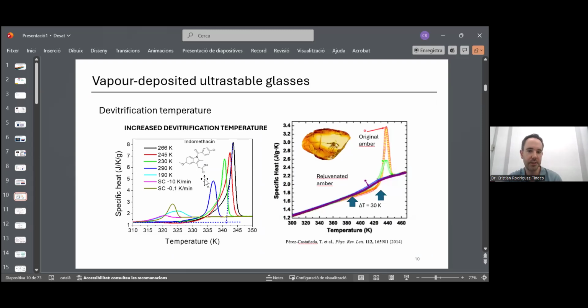Here we can see some examples. So it was with indomethacin, which was one of the first molecules with which the concept of ultrastable glasses was tested. And these are calorimetric measurements. We see here these small bands. These are the ordinary glasses, the glasses that have been formed by cooling from the liquid, at 10 Kelvin per minute or at 0.1 Kelvin per minute. The one prepared at 0.1 Kelvin per minute has the onset of the devitrification, when we change from glass to the liquid, slightly larger, but not significantly larger.